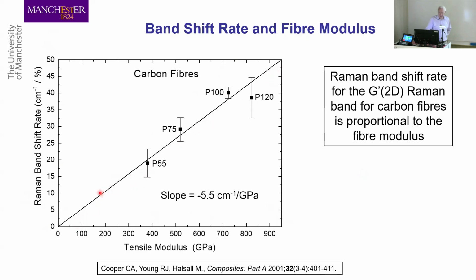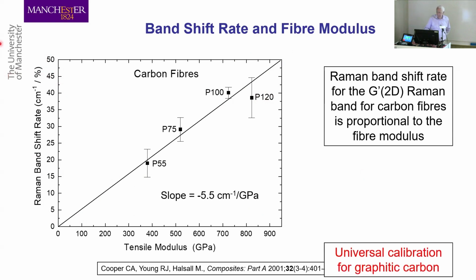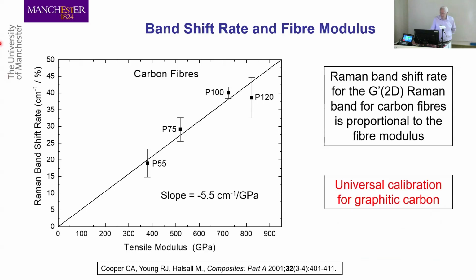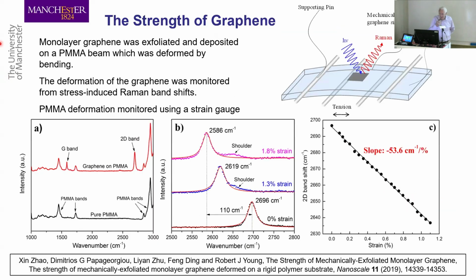Low modulus fibers are down here, high modulus fibers up there. This is our highest modulus fiber with 800 gigapascals, P120 pitch-based fiber, had a shift of over 40. So we found that the shift rate is proportional to the stiffness of the fiber. So it is also a universal calibration for all forms of graphitic carbon, presumably also for graphene. So when we did this experiment on graphene, we found similar things. So we now took our single layer, monolayer graphene, put it onto a plastic beam.